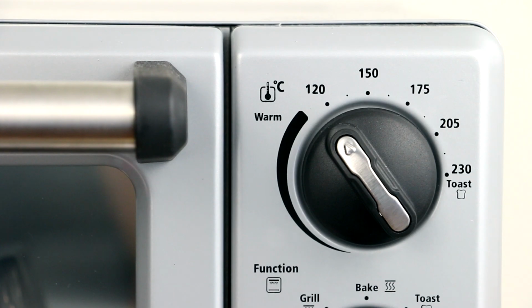Every oven is different. You'll find that most temperature dials are not accurate and they bake much hotter or cooler than what's set. My oven is set to an internal temperature of 130 degrees Celsius on my separate thermometer, but on the actual dial it reads about 115 degrees. As you can see, it's way off, so you want to know how your oven behaves before baking your clay.